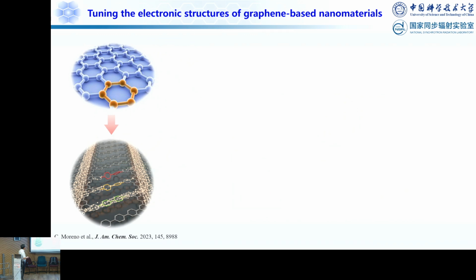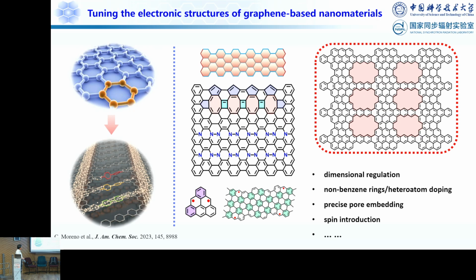But if you want to really use graphene, you have to open the band gap. There are different ways to open the band gap. First is reducing the dimension. For example, you can cut the graphene into graphene nanoribbons or graphene nanosheets, or you can introduce non-benzene rings or heteroatom doping. In the process you can also introduce pores inside, and spin introduction. I want to mention this briefly.